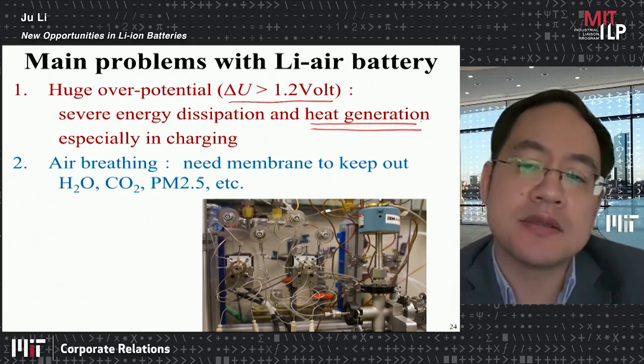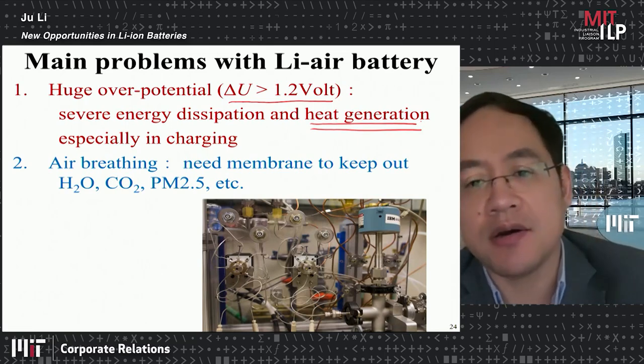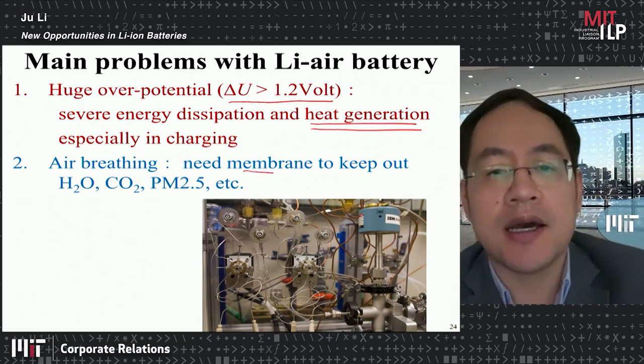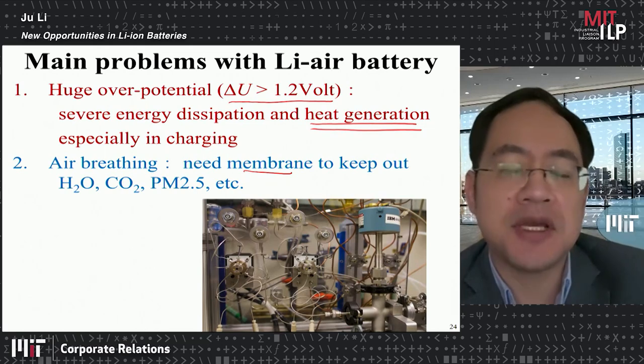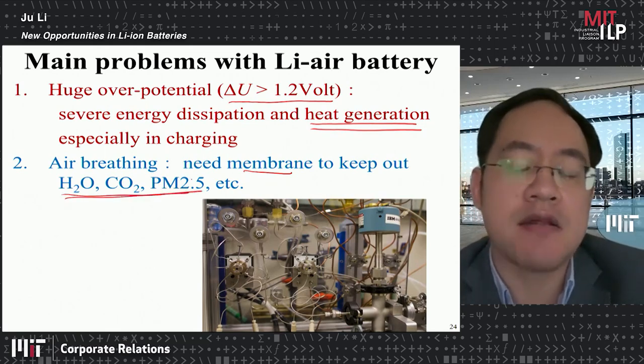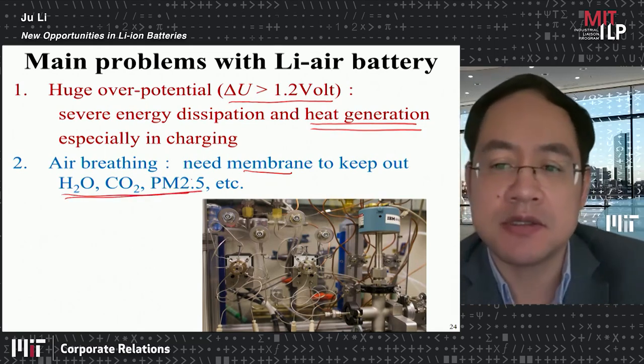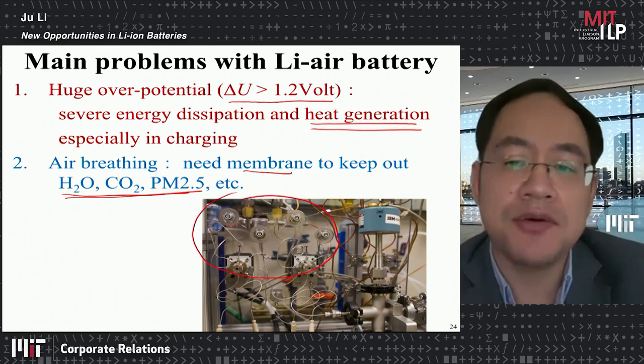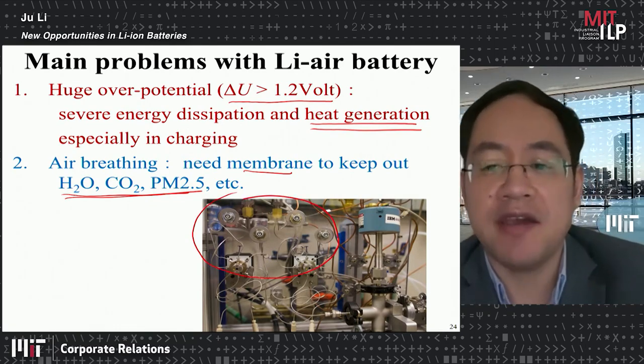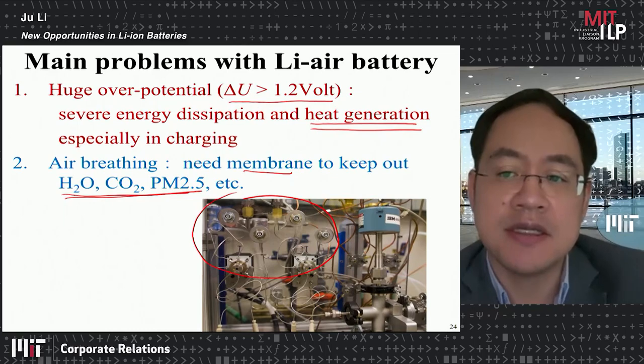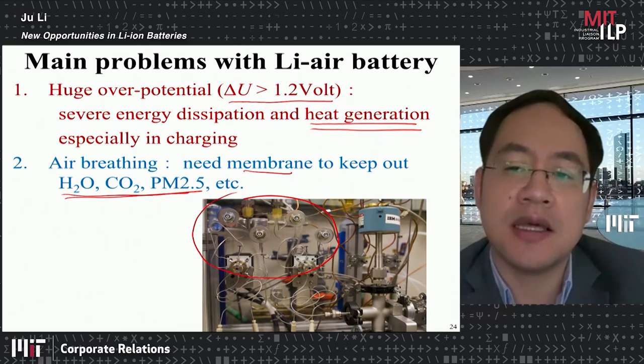And the second problem is the lithium air battery essentially is a fuel cell. You need membranes to actually keep all these other things other than oxygen out from the system. So the auxiliary system that you need is actually much heavier than your active material. So this reduces your system economy.